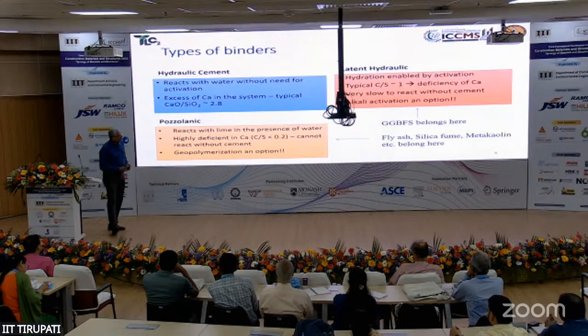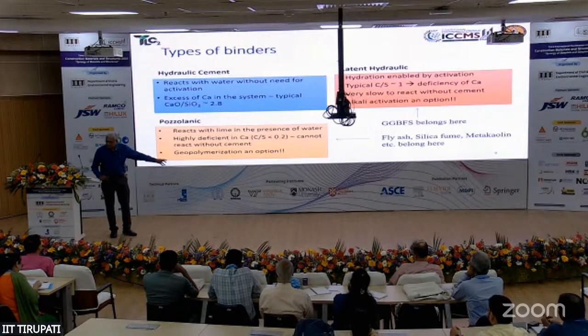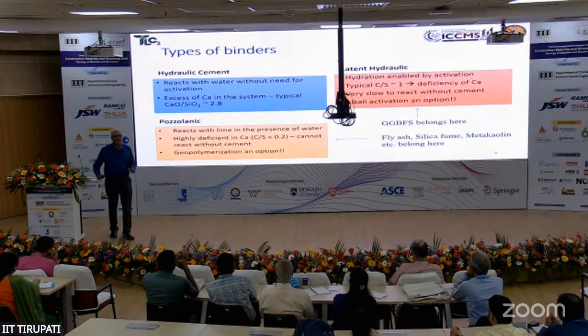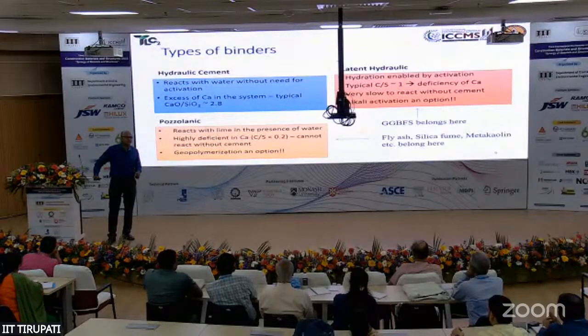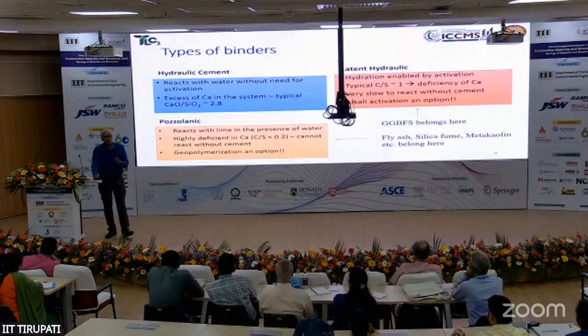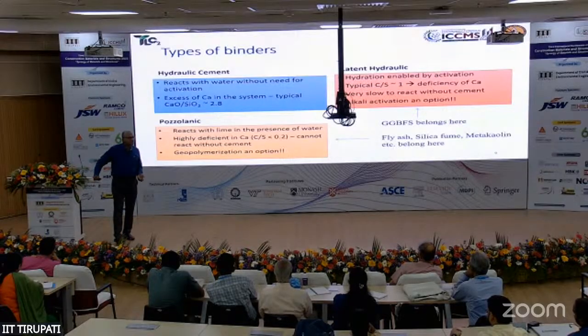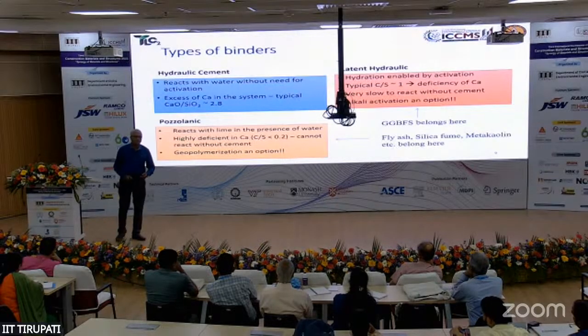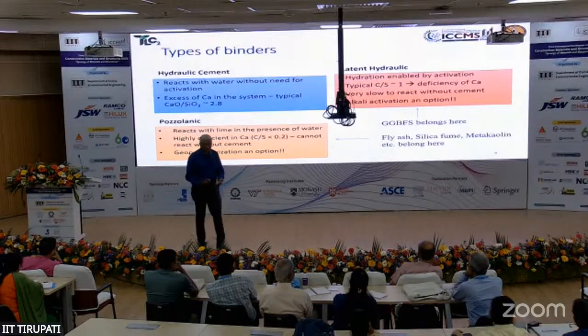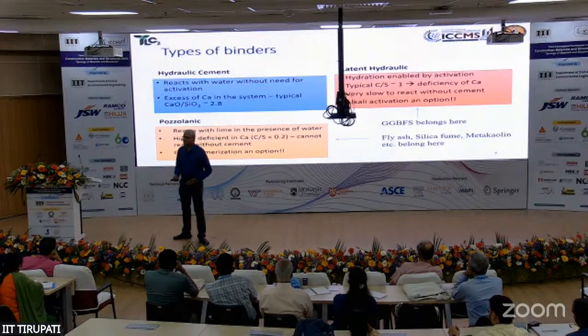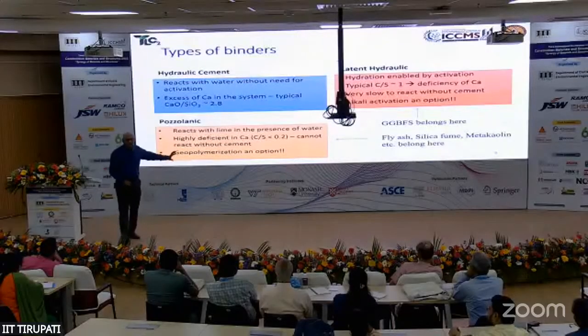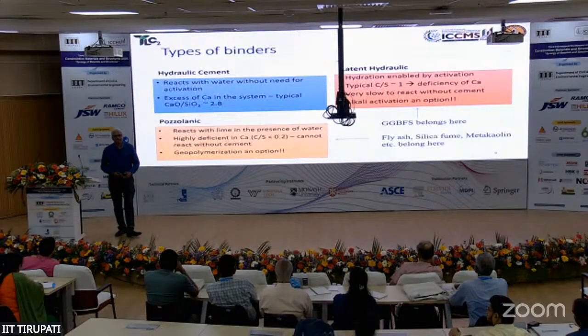So we have, of course, different types of binders. We need to realize what can perform where. So, of course, we have the latent hydraulic binders like slag, which have a fairly good calcium to silicon ratio, which causes activity if you have some sort of activation done using an alkali or a sulfate. But then you have pozzolanic materials, which are mostly rich in silica, and that silica has to be in the amorphous form. So there you have a deficiency of calcium. So you need some sort of a lime-based system, either lime produced from cement hydration or lime added onto the system to induce reactivity in the pozzolanic material. So depending upon the composition of the material that you have as a mineral additive, you can have different kinds of chemistries exhibited by these materials.